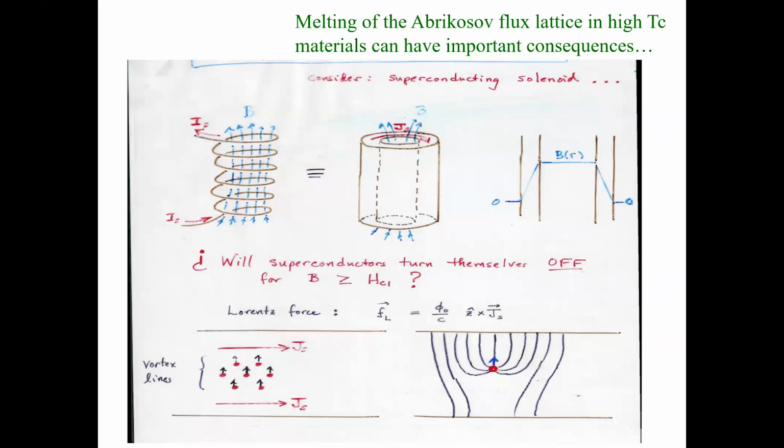So this is a picture of a vortex line that's going from one side of the sample to the other, carrying 2 pi flux with it. And when that happens, you generate a voltage, and your material is no longer a superconductor. So if these lines are free to move as they wish, we'll stop them from moving momentarily. We'll show you how they do that experimentally.